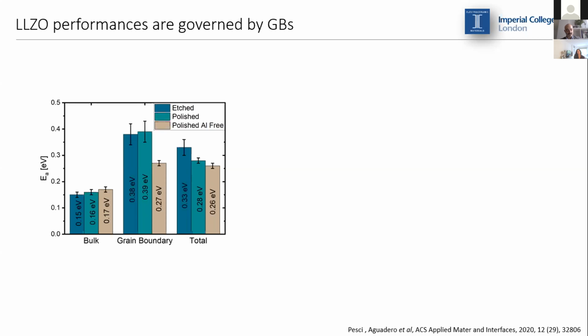However, with the amount of data that we had, we decided to do a little bit of statistics and see how different samples could behave electrochemically. And in this graph in here, I'm comparing the activation energy for bulk and grain boundaries for a set of 3 samples. We have got etched, polished sample, and a polished sample aluminum-free that was actually synthesized in magnesia crucible. So we are ruling out the presence of aluminum at the grain boundaries. And if you look at the bulk, it seems not to be affected much by the amount of aluminum in the sample. However, if we look at the grain boundaries, we see a consistent and a sensible decrease in the activation energy for the aluminum-free sample.